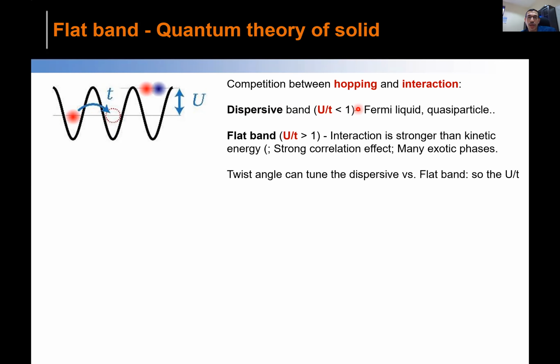Most of the metals and systems we are very familiar with are like this, and conventionally you can characterize them as a Fermi liquid, with quasi-particles carrying electronic charge and so on. However, if you have the other regime, for example the flat band I was talking about, which means your dispersion is dispersionless, what does it mean? Your velocity is extremely low. As a result, the electrons will see each other, and the interaction will be much higher. So the U for this kind of system is the other limit, for the flat band: U over t will be higher than 1. And in this case, many exotic phases and correlation effects will dictate the properties of the solid.